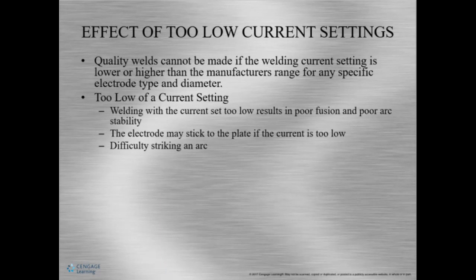So if the amperage or the heat settings are incorrect, it makes it impossible to have a good weld. When the amperage is too low, there's poor fusion, poor arc stability, and poor penetration. On the other hand, the arc may be difficult to strike, or the electrode may even stick to the plate. So how do you tell whether the current or the amperage is too low? Okay, well, the weld will seem really thin and it'll look kind of like an earthworm.